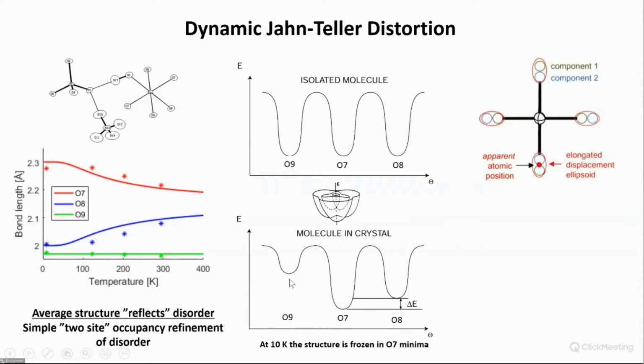So at lowest temperature, this is the structure we measured in my charge density study. But then as we heat up, we start populating also some molecules where the O8 is stretched. And this is why we see this apparent bond length change. So really, the average structure over the crystal just has two components on each oxygen site. And in structural crystallography, this is of course very well known: you just add two sites, you have an occupancy, and you can refine it.